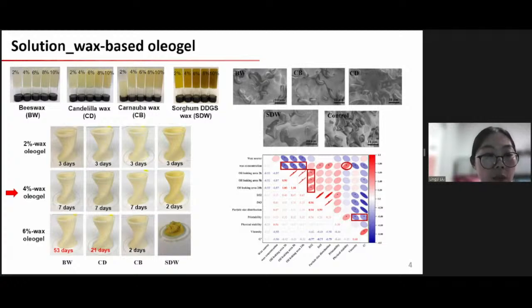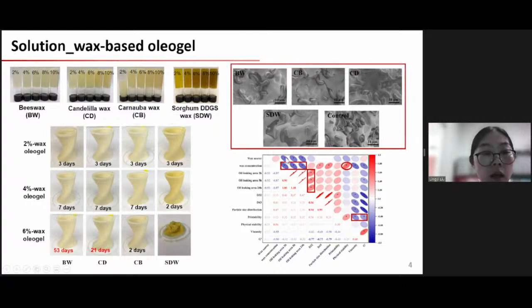For commercial wax oleogel, the printability was good when the wax concentration in the oleogel ranged from 2% to 6%. Well, for the lab-extracted wax, the sorghum DDGS wax, since this wax only contains 50% wax and it also contains 40% oil inside, the shape will collapse during the printing when the wax concentration reached 6% in the oleogel. With the SEM results, we can see here the microstructure actually became loosened due to the nonpolar property of wax. So if the wax concentration in the oleogel increased to 8% or higher, the printing failed for all the oleogel paste.